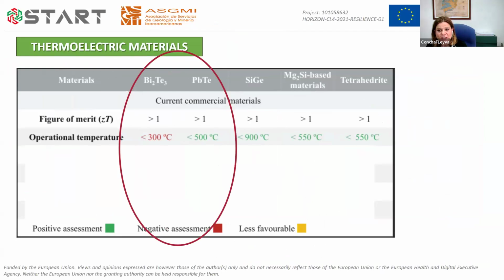In this picture, we can see the materials currently used as thermoelectric materials. The color code of green, red, and yellow indicates the favorability of the material characteristics. Good thermoelectric materials have a figure of merit just above 1, and you can see in the first line, at certain temperatures. The best materials for commercial devices used at low to mid temperatures, up to 500 degrees Celsius, are based on telluride, like the first two columns you can see on the screen.